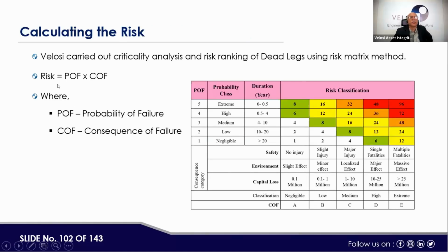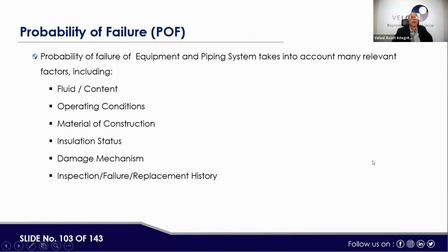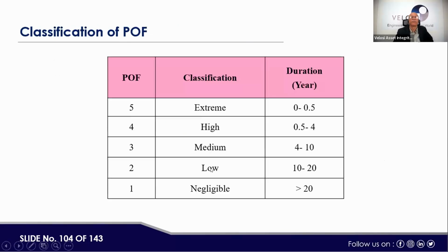Now, the risk PF and CF and this risk matrix which is used. Under probability, we have considered fluid content, operating conditions, material of construction, insulation status, damage mechanism, inspection, failure, and replacement history. And this is basically the condition of POF, on a 1 to 5 scale, where 1 means the failure rate is 1 out of 20 years, and 5 means failure could occur between 0 to half a year.